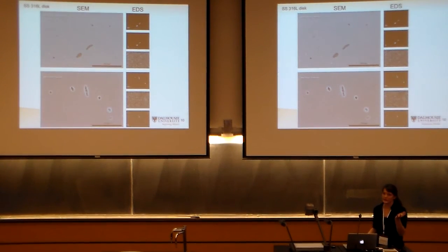I'd also like to mention our stainless steel discs. They have shown very similar results. However, due to the larger surface area, they're a couple of millimeters in size as opposed to our wires, which are only 380 micrometers in size, there have been a couple of inconsistencies, and so we're just following up on those. So here, a scanning electron microscopy scan before and after, as well as our energy dispersive X-ray spectroscopy scan.